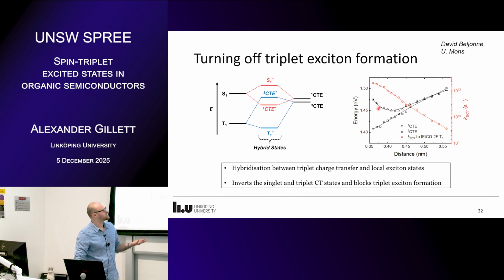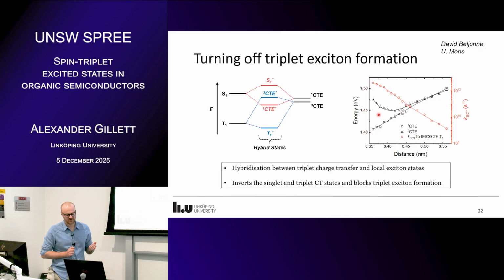And what that means in reality probably is that for your electron hole pair, the most stable configuration is not necessarily to sit right at the interface, but maybe a little bit back from the interface. Maybe at a molecule further back, or in some kind of regime with more disorder or greater pi-pi distance at the interface. This has quite a big effect on the electron transfer rate that goes from the triplet charge transfer state through to the molecular triplet.